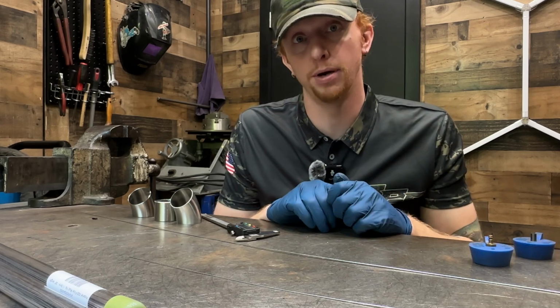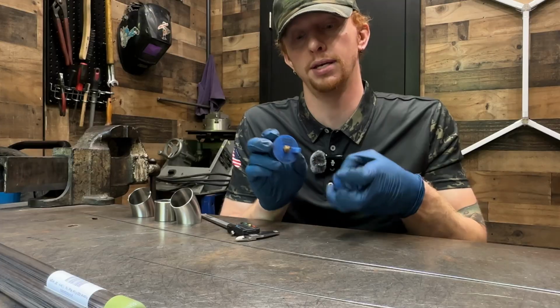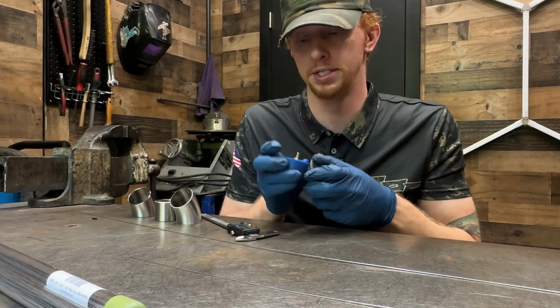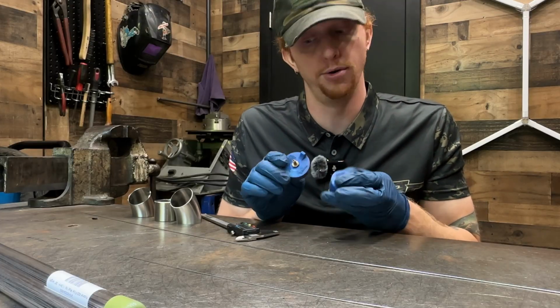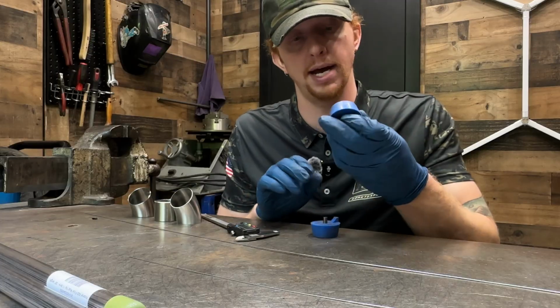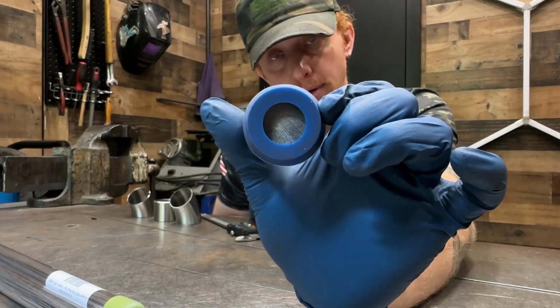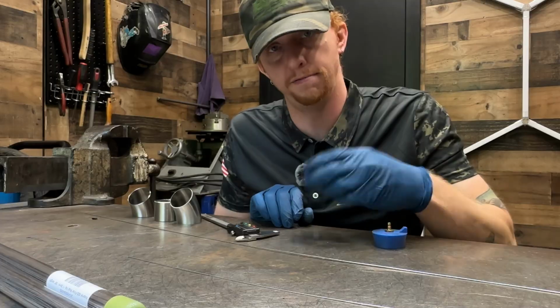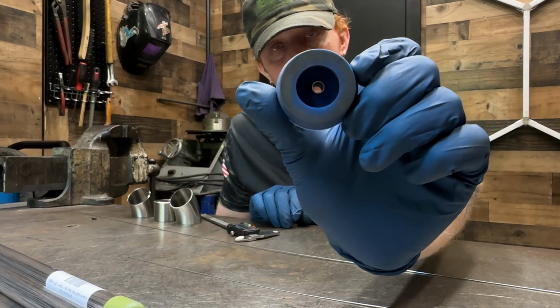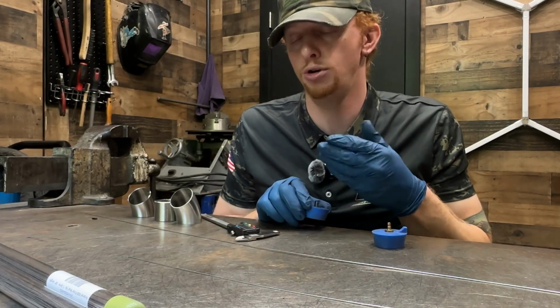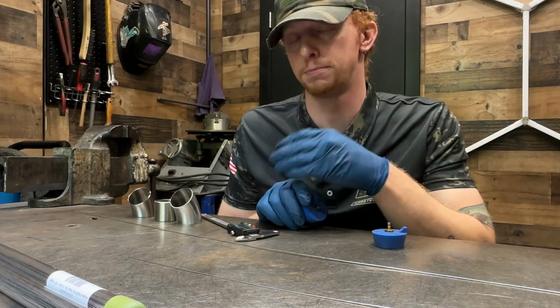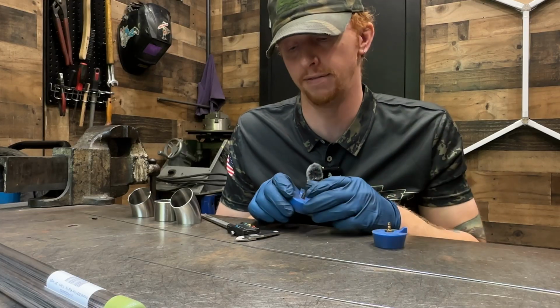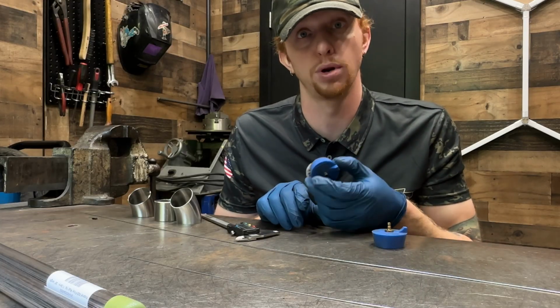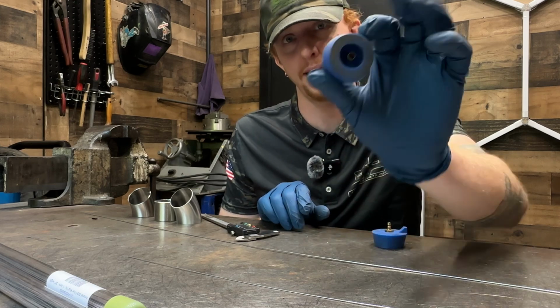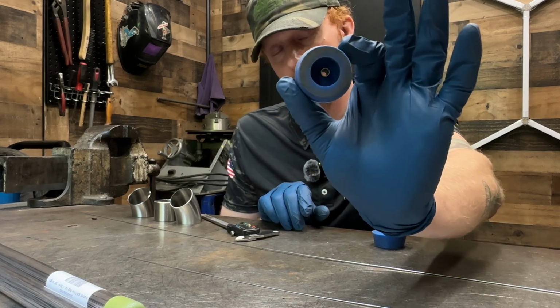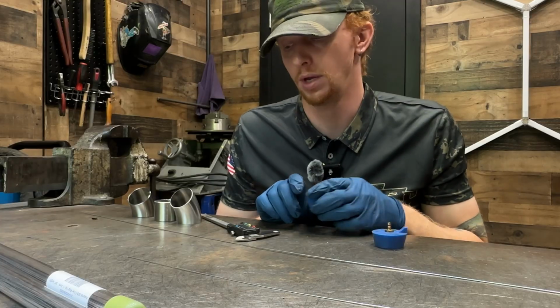To aid in the back purging process, I'll be using TIG Aesthetics back purge plugs. These are silicone plugs. The feed side has a diffuser screen, if you guys can see that there, whereas the vent side has just a tube. To back purge, with the point being to displace atmospheric air from the inside of the piece, you need to have some sort of a weep or a vent hole, which the plug with the tube in it serves as.